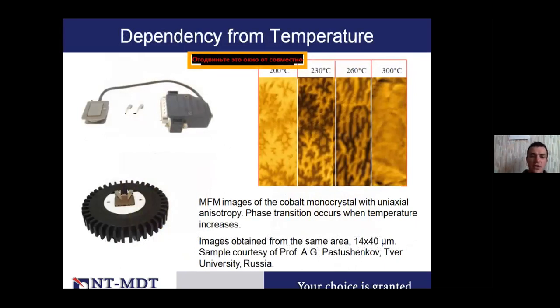Also, atomic force microscopy allows us to measure some properties depending on the temperature and heating control. So here we have different types of heating stages, which can heat our sample or cool our sample at different levels of temperature. And you can see on the right, this is a magnetic force microscopy image of a cobalt monocrystal, which depends on the temperature of the sample. You can see how the magnetic properties change depending on the temperature from 200 degrees to 300 degrees. You can see that the structure is totally reduced under very high temperature.